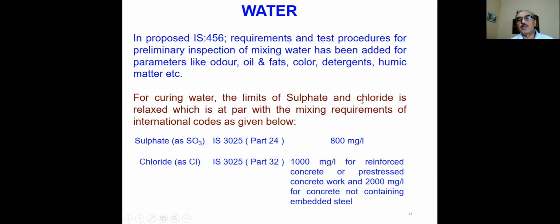For curing water also, we are not changing much of the specification, but for example, chlorides up to 1000 milligram per liter - this is commonly used in many countries even for RCC - so this much we are permitting in curing water. Because for curing water, if we say 500, people don't have access, and without telling anyone, they use more anyway. So we are giving some liberty, but if it is more than that, they have to use different water. Sulfates and chlorides - some minor changes have been made here for curing water.